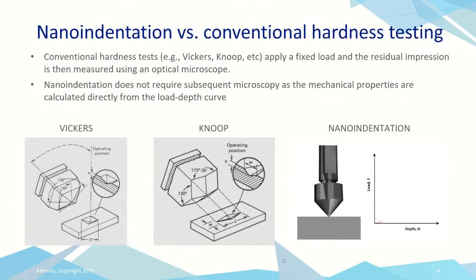Okay, so just to compare to conventional indentation, for those that are not familiar with nanoindentation, at the conventional scale, we make an indent with an indenter of known geometry, could be Vickers, could be Knoop, and then we need to measure the size of that indent under a microscope. With nanoindentation, the indent is so small, we can't do that because we can't see it. So we have to get our calculation of data from the load depth curve itself.